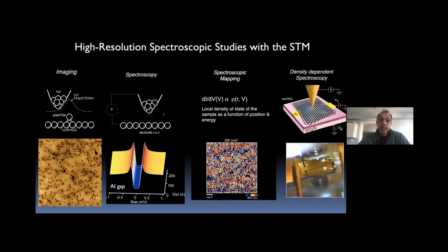But what excited us about 2D materials in general, and in particular this system with strong correlations, is that now we can add to the technique of doing spectroscopic measurement the ability to in situ tune the carrier concentration. So this is a very exciting knob just by itself from the perspective of being able to do new experiments using the STM. You can locally control the carrier concentration and actually go between, as I'll show you, interacting and non-interacting limit in the same clean material system.